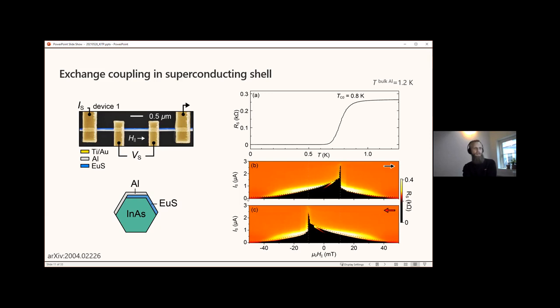Starting at negative 50 millitesla, the superconductivity is suppressed but revives quickly, and then increases towards magnetic field zero, and keeps increasing when we pass the zero. This is roughly where the zero is. It spikes around positive 10 millitesla, drops abruptly, and then smoothly decreases again and diminishes around 50 millitesla. The picture inverts itself when we sweep the magnetic field the opposite way. We find that the spike of the supercurrent, the critical current, is around negative 10 millitesla on the other side of zero. This indicates hysteresis in the system, implying that the aluminum is well proximitized by the europium sulfide, yet it doesn't suppress the superconductivity fully.